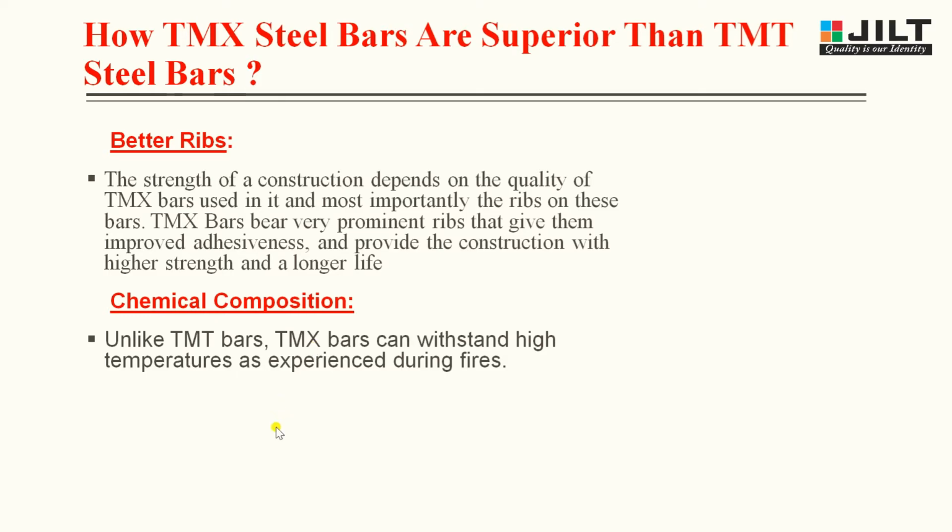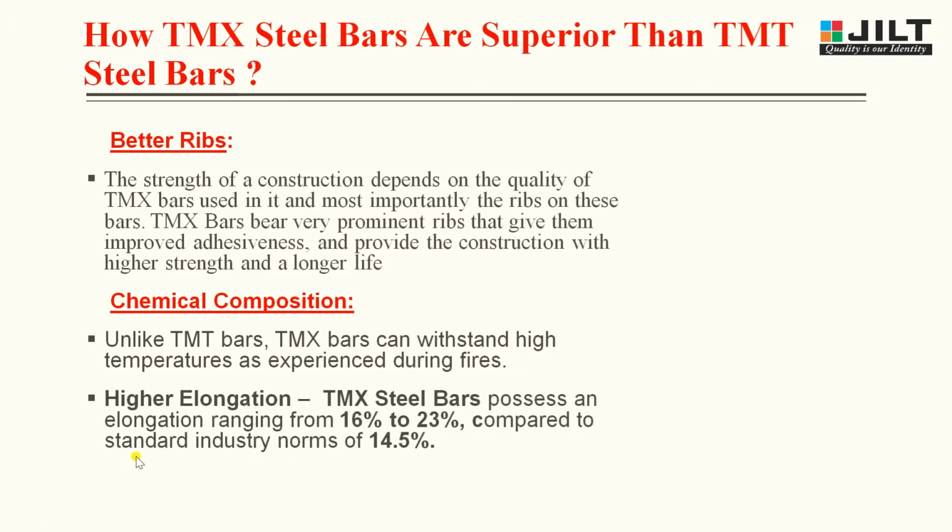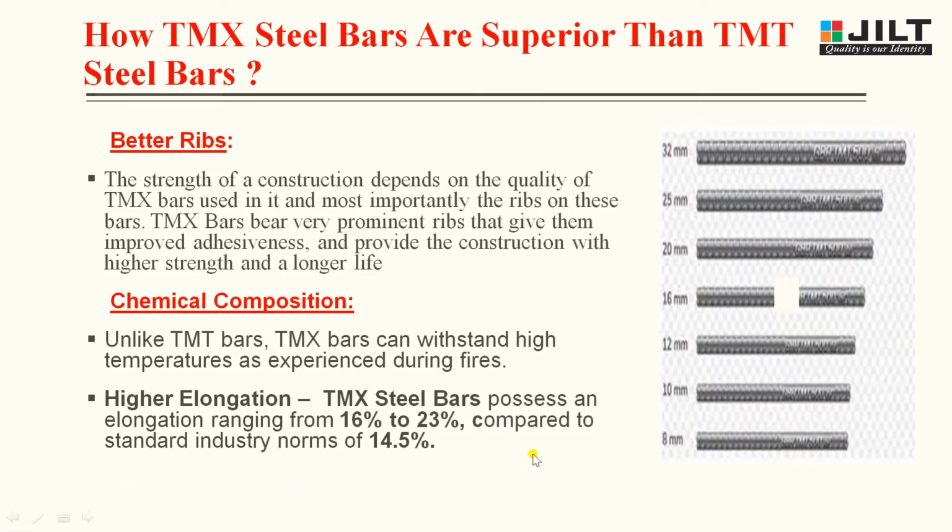Another one reason that is chemical composition. Unlike TMT bars, TMX bars can withstand high temperature as experienced during fires. So just now I explained the TMX bar will having more fire resistance. Higher elongation is also available. So TMX steel bar possess an elongation ranging from 16% to 23% compared to standard industry norms at 14.5%.